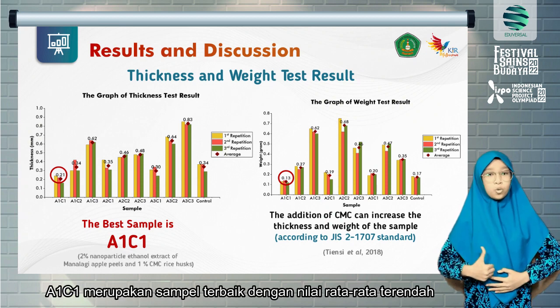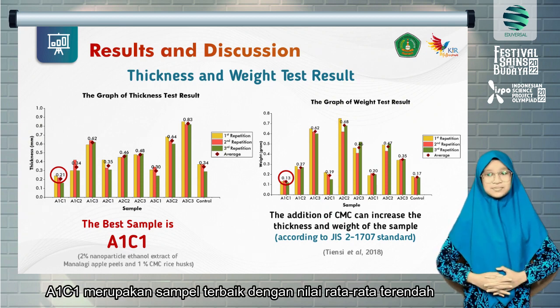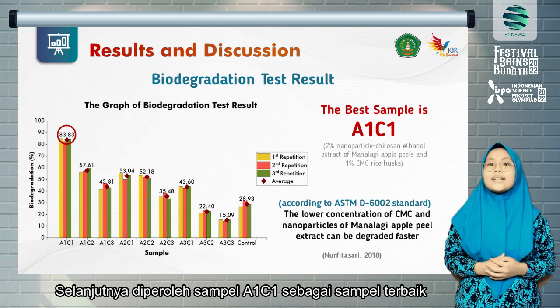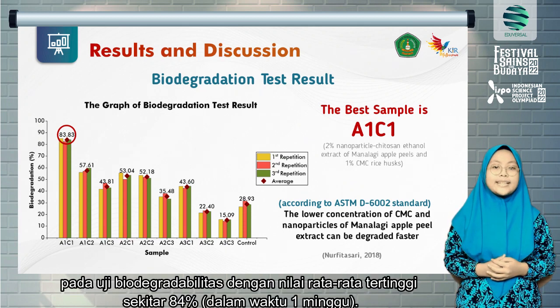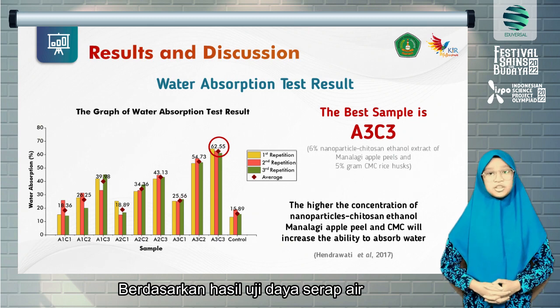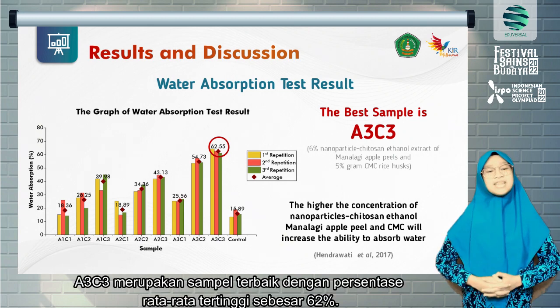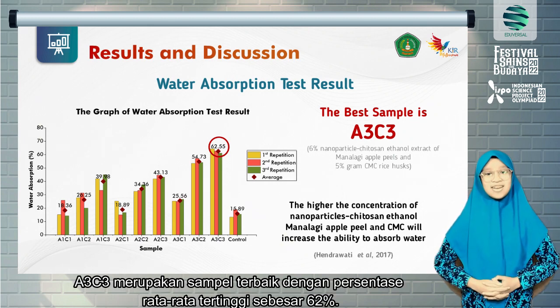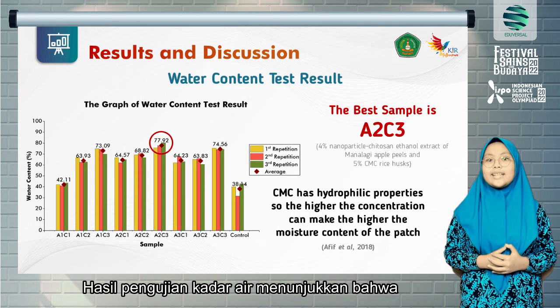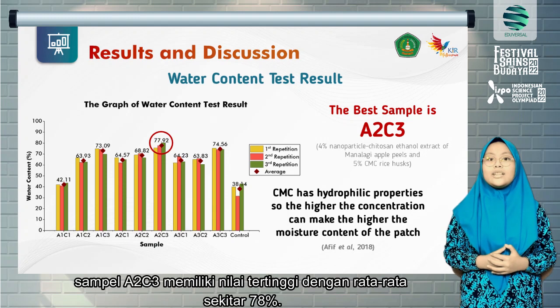These are the results of the hydrogel patch characteristic test on the thickness and weight parameters. A1C1 is the best sample with the lowest average value. Furthermore, the A1C1 sample was obtained as the best sample in the biodegradability test with the highest average degradation of about 84%. Based on the water absorption test result, A3C3 is the best sample with the highest average percentage of 62%. The water content test result shows that the A2C3 sample has the highest value with an average of about 78%.